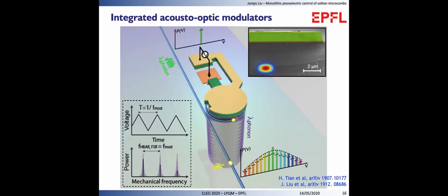This slide shows how the device looks. When applying an AC driving voltage on the aluminum nitride, the stress effect or the bulk acoustic wave can be induced, which modulates the incident photons. If a soliton is generated in the microresonator, all the soliton comb lines are modulated at the same speed. With this new capability, we can control and modulate the soliton state by external RF driving.